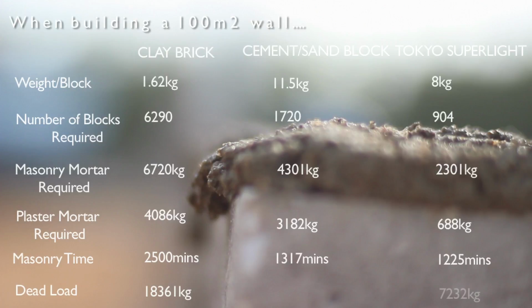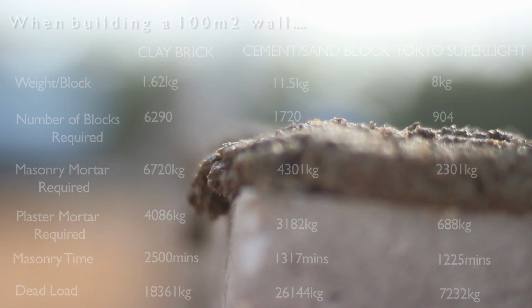D. The time it takes to build a Tokyo Superlight wall is half that of the time it takes to build a brick wall, and 10% less than the time it takes to build a wall out of cement sand blocks. E. The final dead loads for each wall after mortar and plastering provide quite sparse results, with a wall built out of Tokyo Superlight weighing 60% less than a clay brick wall of the same size, and more than 60% less than a cement sand wall. Imagine the savings on steel reinforcement if you were building a skyscraper.